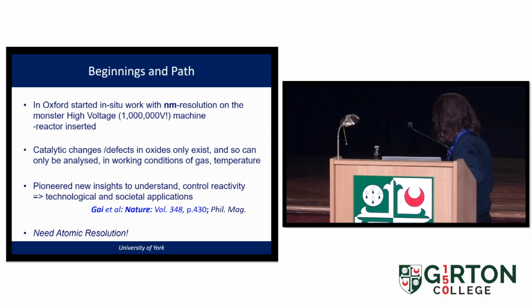And in the beginning, I had worked on in situ microscopy at Oxford. I built a reactor, which is something like that. I could put it in the microscope, connect various gases, and the machine was 1 million volts and it was like 20 meters tall. So every time I had to do the experiment, I had to put it in, put the gases and do the reaction and take it out, etc. It was really a pain. But I got to nanometer resolution, which was the best at the time, and so we could publish it in good papers. It also showed us that you have to have a reaction environment to see the reaction. If you take it out in a vacuum, you wouldn't get it. So all the changes occurred under gas and temperature environments.